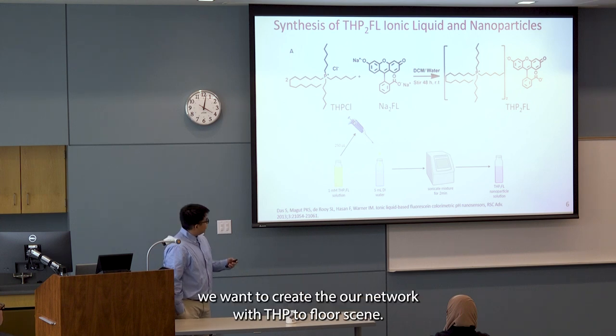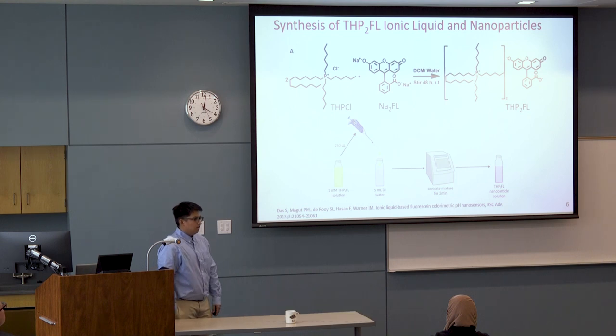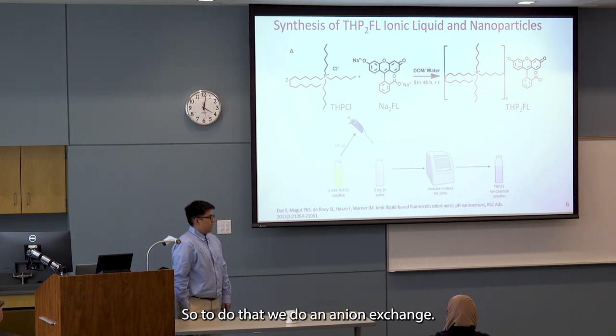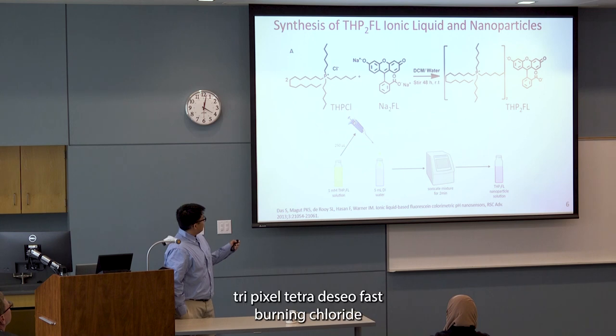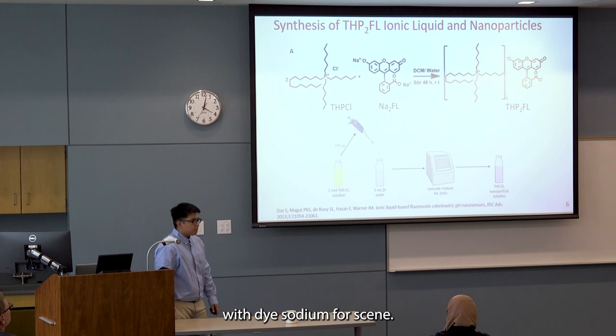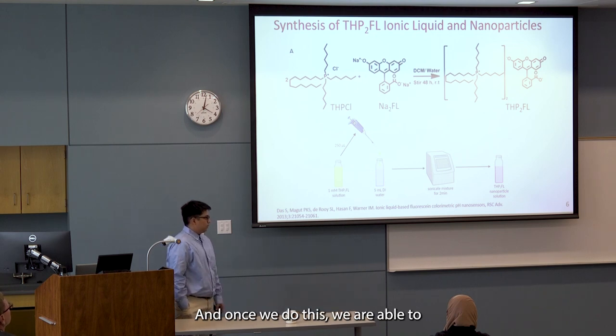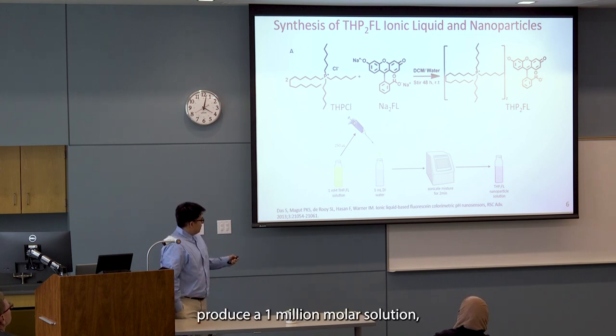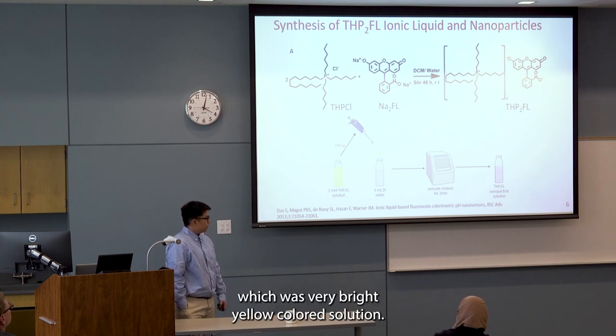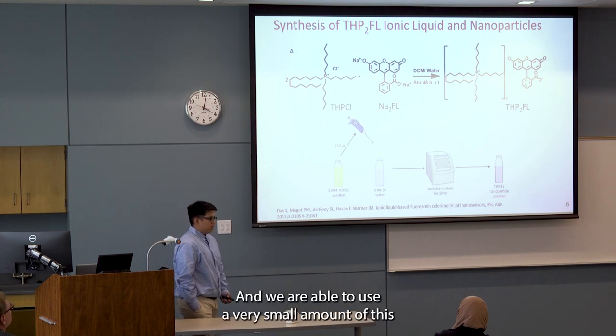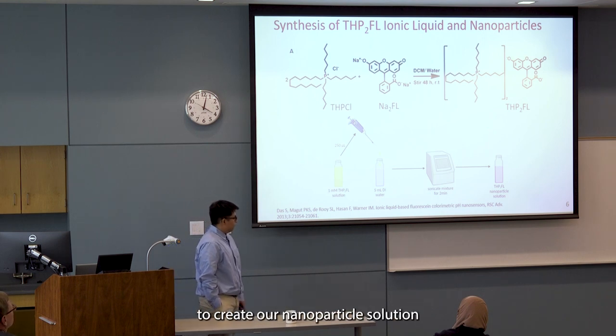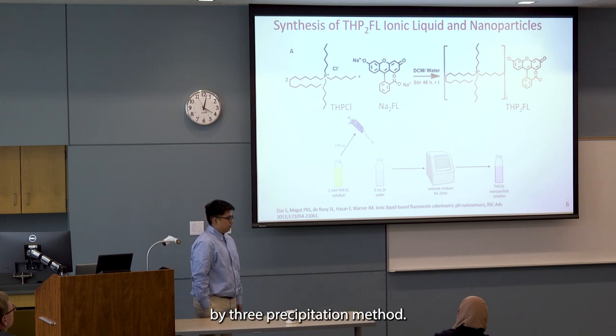So to start off, we want to create the ionic liquid THP2 fluorescein. And so to do that, we do an anion exchange of trihexyl tetradecyl phosphonium chloride with disodium fluorescein. And once we do this, we are able to produce a 1 millimolar solution, which was a very bright yellow colored solution. And we are able to use a very small amount of this to create our nanoparticle solution by the reprecipitation method.